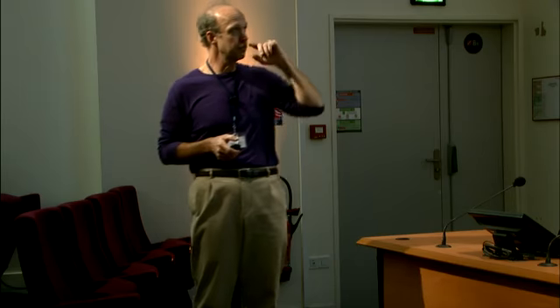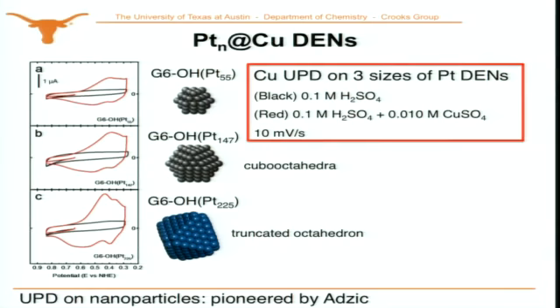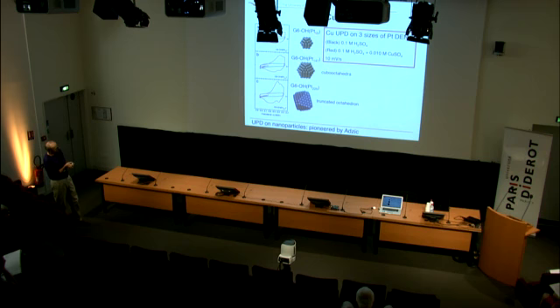Okay, so here are some of our first experiments. This is, in fact, copper underpotential deposition on platinum dendrimer-encapsulated nanoparticles of 3 different sizes. The reason we use these numbers of atoms, 55, 147, is that these are magic numbers for closed shell cubo-octahedral particles. Okay, and so here's the first one.